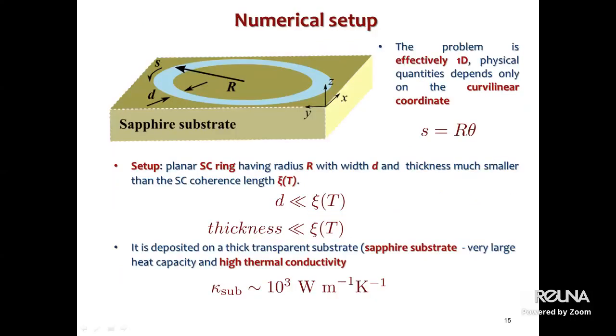Now, motivated by the above discussed experimental findings, a few of which I presented, we have performed a series of investigations of the generation of current-carrying states due to the inverse Faraday effect. For that, we consider a system which consists of a planar superconducting ring having radius r and width d, and thickness much smaller than the superconducting coherence length. The ring is deposited on a thick, transparent substrate with a very large heat capacity and thermal conductivity to ensure a high cooling rate. This is the system we work with.